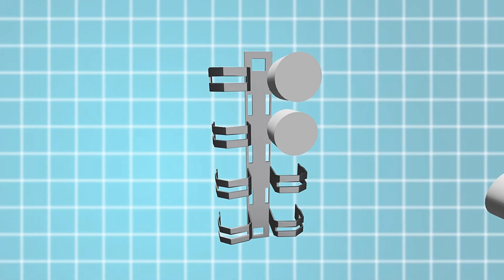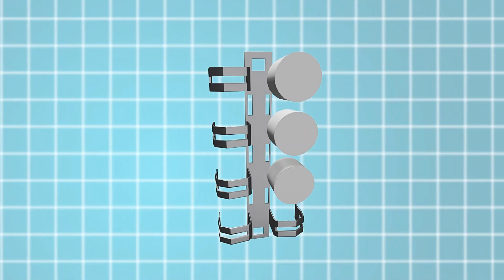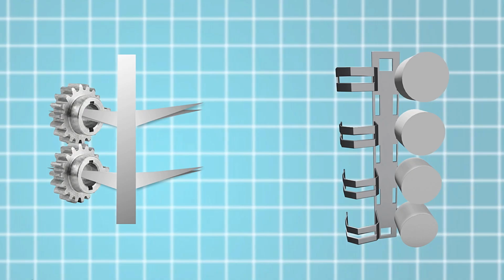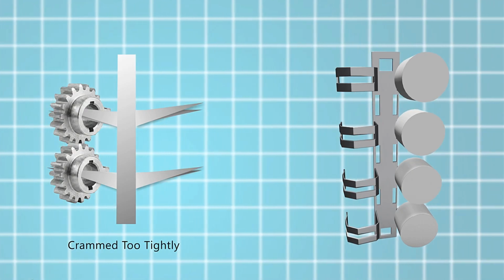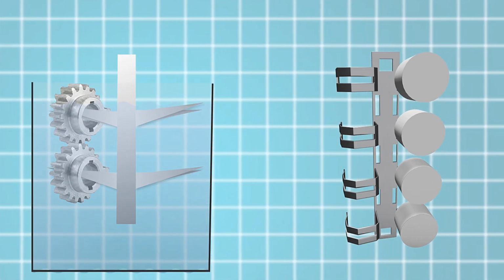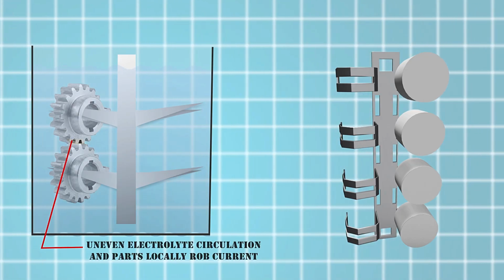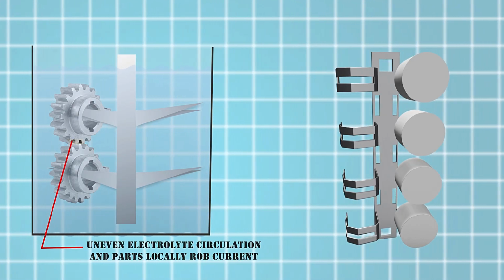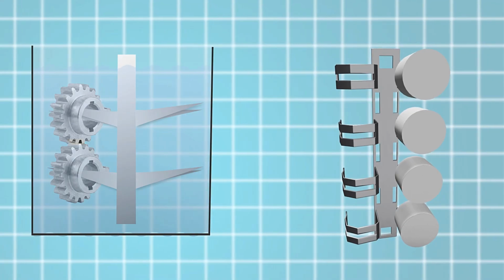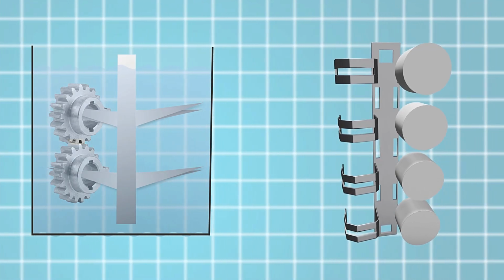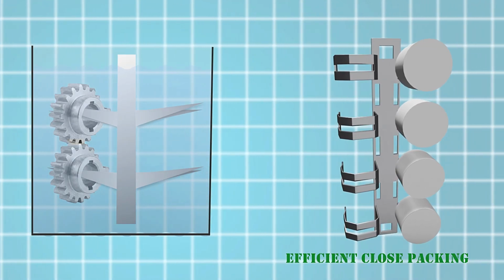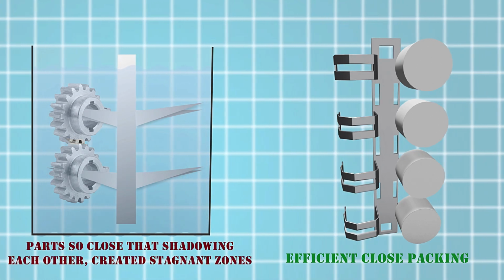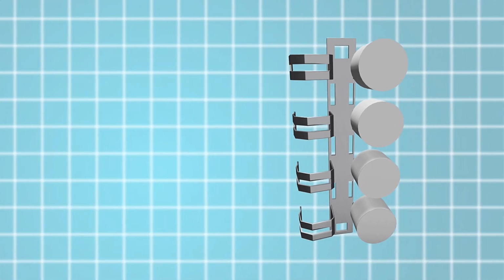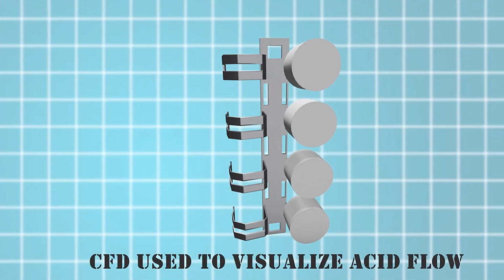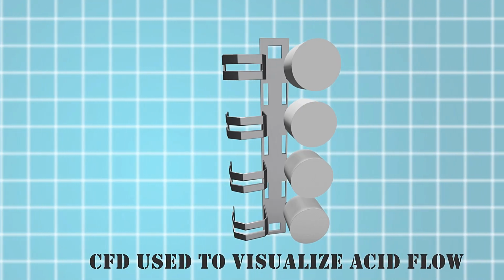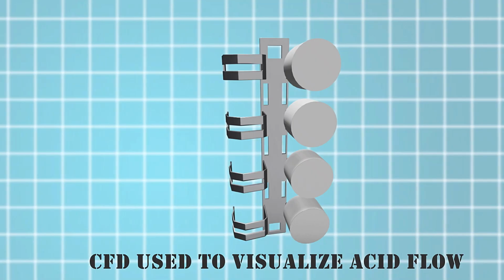Spacing between parts is crucial for both solution flow and electrical field distribution. Cram them too tight to boost throughput, and you risk shielding and uneven coating because the electrolyte doesn't circulate evenly, where the parts locally rob current from each other. High-density rack design is an art of strategic spacing. Pack parts close enough for efficiency, but not so close that they shadow each other or create stagnant zones in the tank. The best engineers use CFD, or computational fluid dynamics, envisioning how acid will flow around each widget.